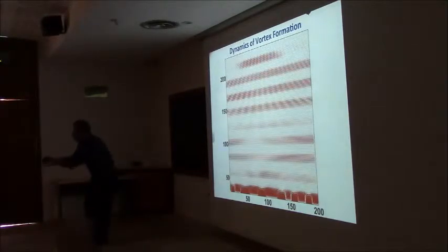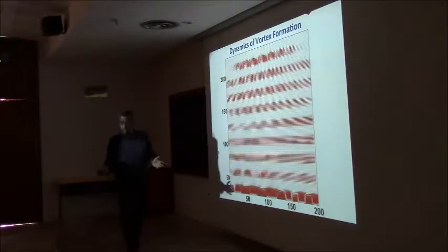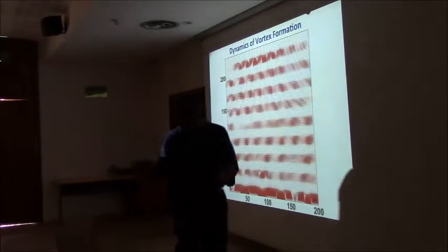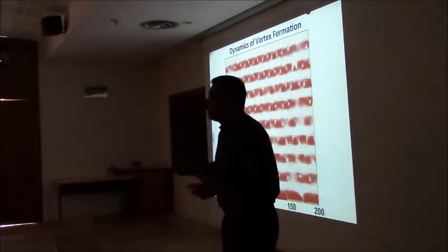Sound wave, yes, acoustic phonon mode, right? We're not talking about optical phonons here, although they exist. We're talking about acoustic phonons. So the approximate thing is approximately of that order. It happens in a few picoseconds, maybe 10 picoseconds or so. In the computer, we don't know this experimentally. So you can think of the strain wave propagating with something like the acoustic phonon mode, or the velocity of sound.